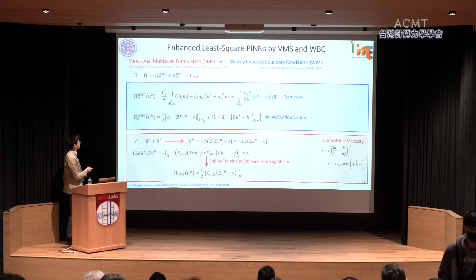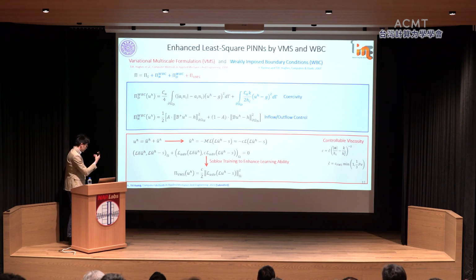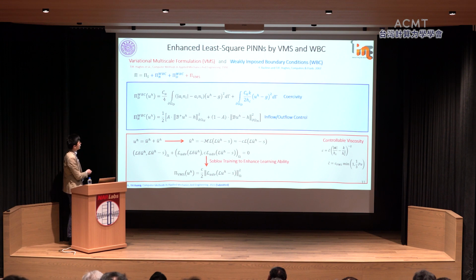Okay, so this is for the boundary. For the non-convergence or learning ability issue, although I use least square, I can still do multi-scale decomposition. You can do something like what Professor JS did, to use RK for the coarse scale and a neural network for the fine scale to derive the scheme. But here I didn't do that, I just used a neural network for everything. So you can substitute it into the least square formulation, and then take a variation to derive the fine scale solution, and eventually this will be the final equation.